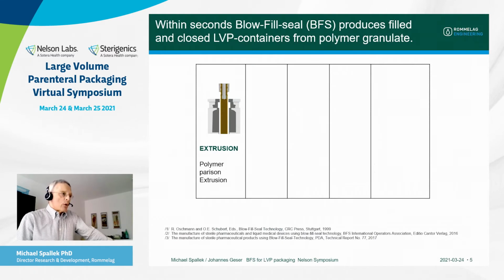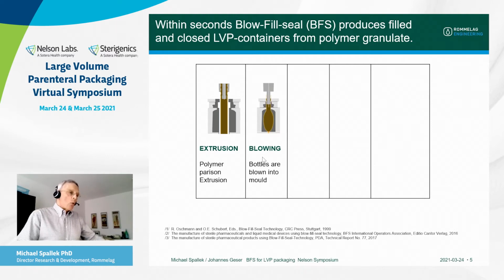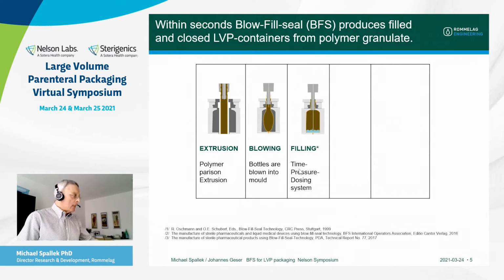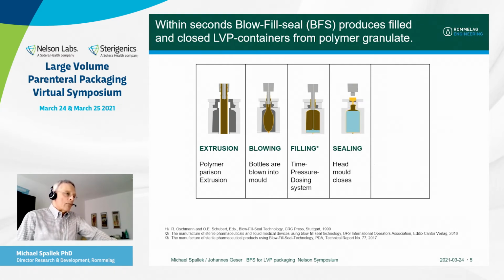So our technology, the blow fill and seal technology, is based on that technology. We extrude the parison into a mold. Second step is blowing with sterile air into the still deformable warm container to shape the container into a bottle, for example. Next step is filling immediately after blowing, because we have a combined blowing and filling nozzle. Then immediately after that, sealing takes place with the head mold that closes and weld seals the container. And the last step is